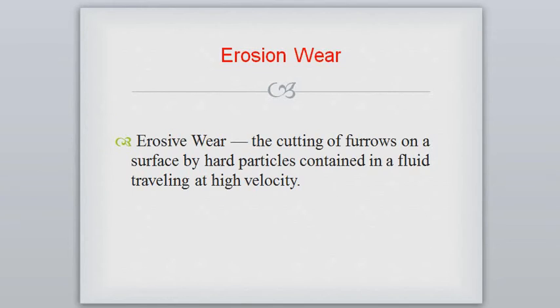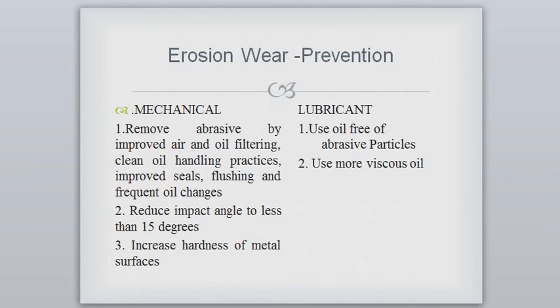Next is erosive wear. Erosive wear is a cutting of furrows on the surface by hard particles contained in fluid traveling at high velocity, such as sand and hard asperities. Preventions: mechanically, remove abrasives by improved air and oil filtering, reduce the impact angle to less than 15 degrees, and increase hardness of the metal surface. For lubricant, use oil free of abrasive particles and use more viscous fluid or oil.